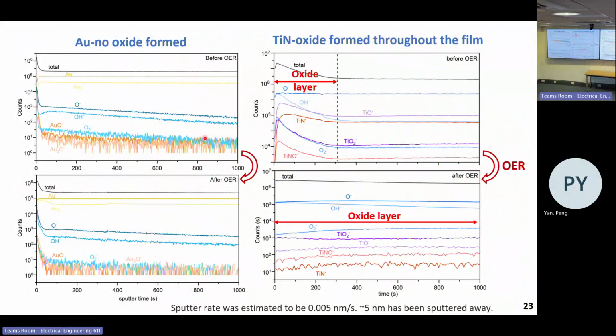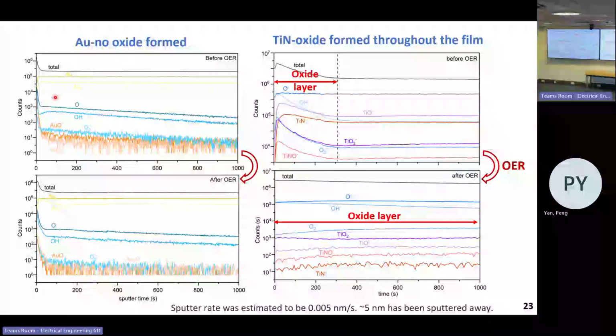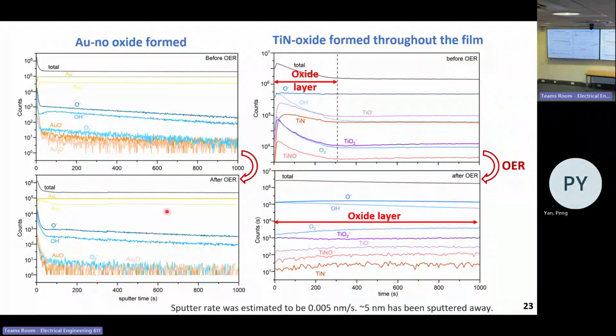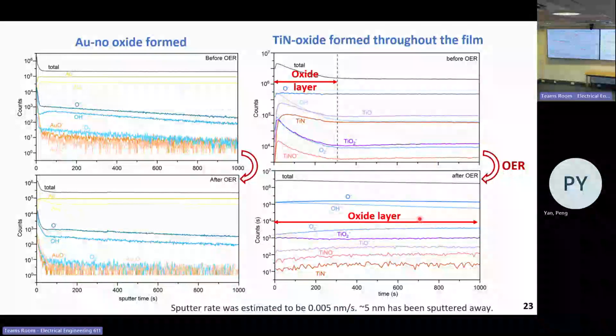We did depth profiling before and after water oxygen evolution, and on gold there is no clear oxide layer formed after water oxidation, but this oxide layer has formed throughout the film on titanium nitride. That might explain why there's no activity at all at the end of the reaction.